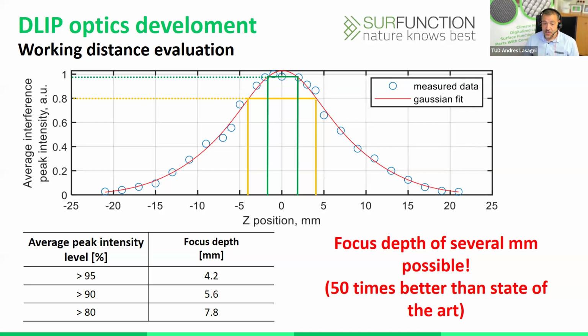That is what is outstanding in this new optical head, because what we observe here is the average intensity of the interference maxima, depending on the set position. So this is, again, the distance between the head and our surface. And you can see that we can keep an average peak intensity level of 80%, let's say, in a depth of almost 8 millimeters. In other words, if the position from your optical head to your surface changes by 8 millimeters, you are going to get more or less the same results.